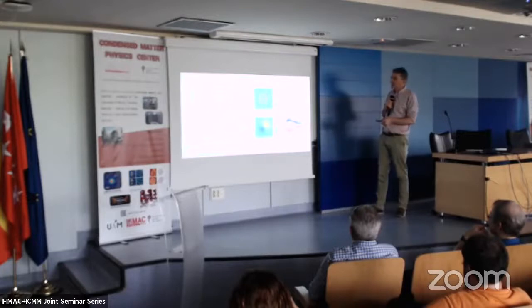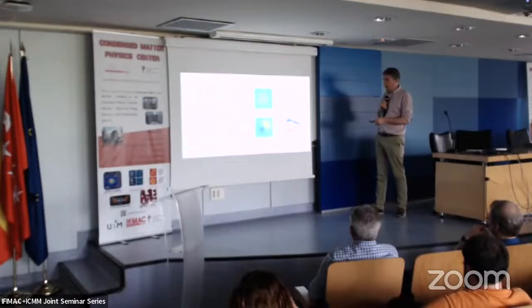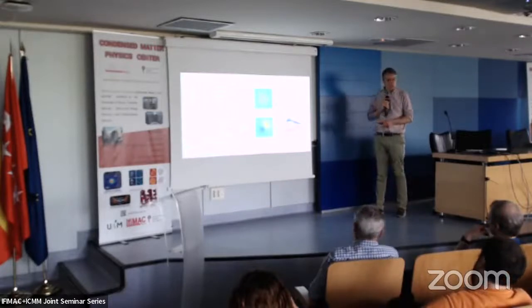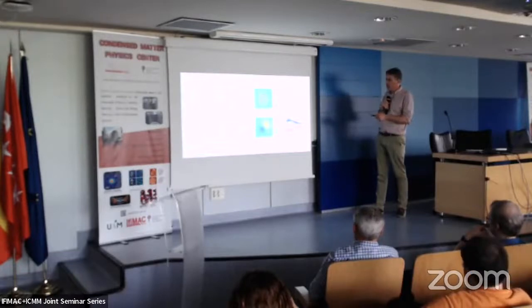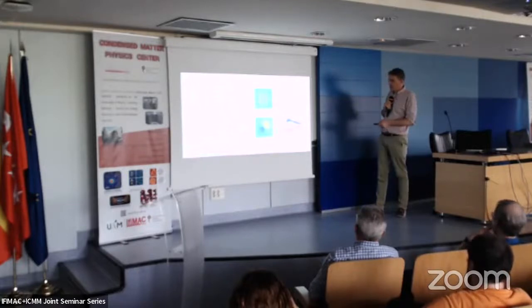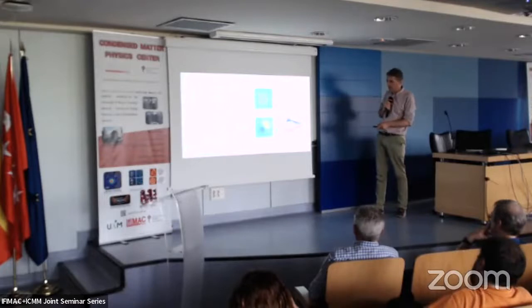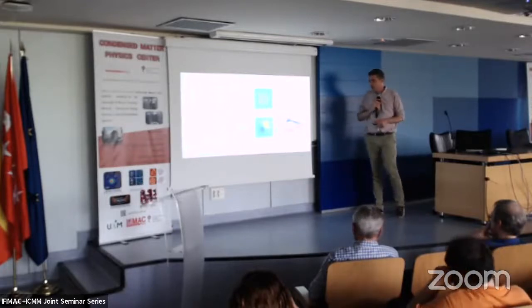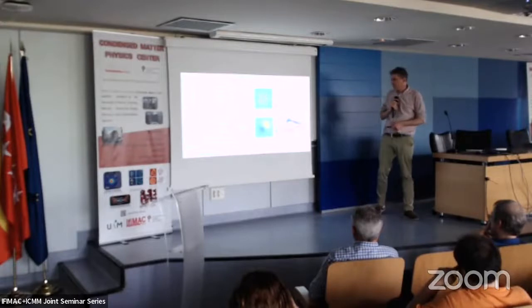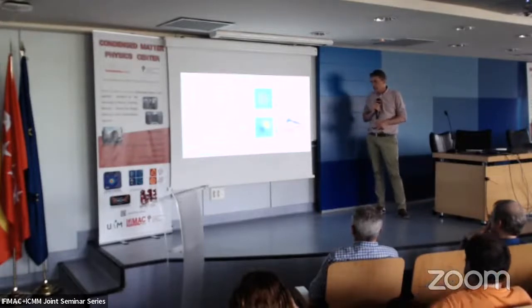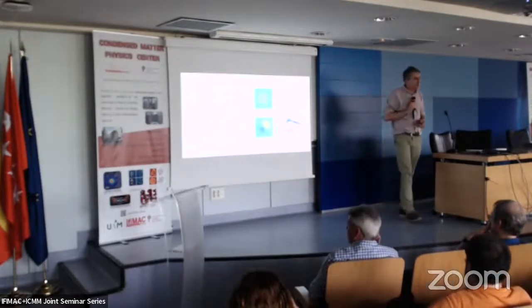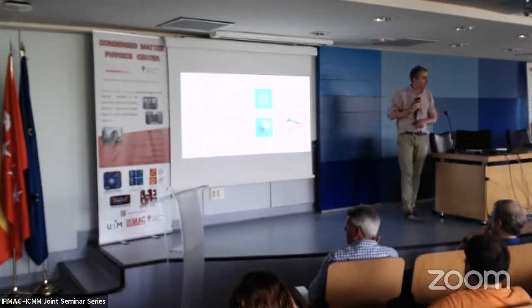Now, this happens when the Fermi wavelength is relatively sharp with respect to the interlevel distance. When the interlevel distance is small or the Fermi wavelength is broadened, this of course destroys all these waves and the whole signal is killed. However, the electron-hole asymmetry remains. If you go in one direction, you have something which goes like this. In the other direction, you have something which goes like this. So as Alfredo noted, this electron-hole asymmetry is related to the band structure of the superconductor, and is inverted if you have electrons or holes.